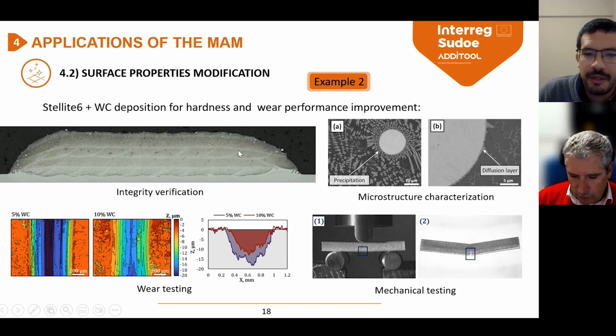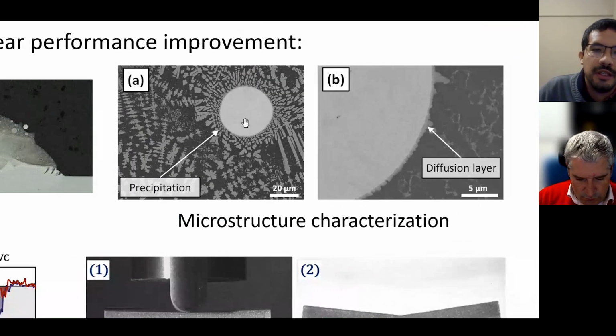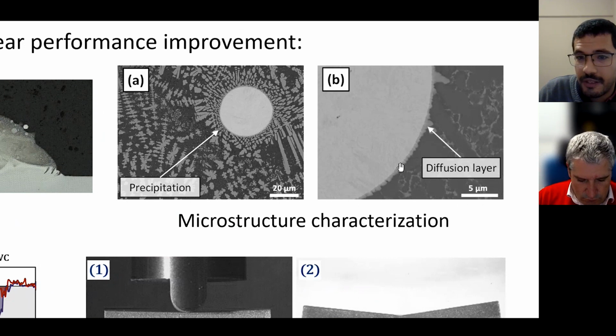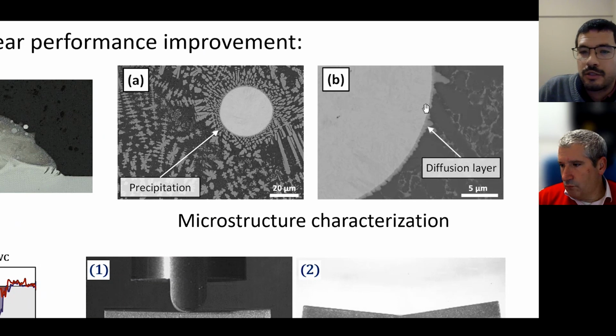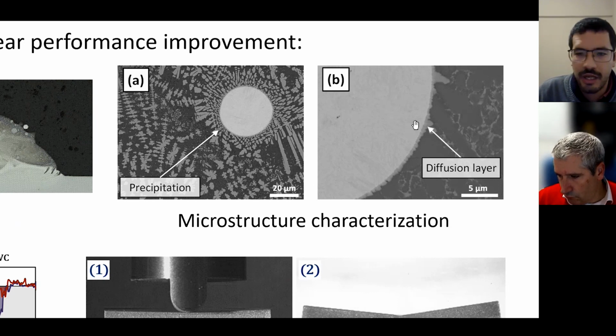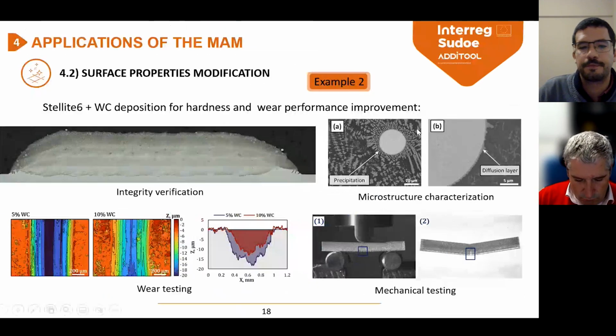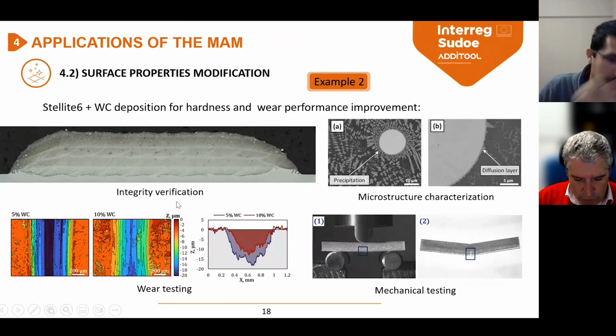Also, as we have a metal matrix composite, we perform an evaluation of the bonding between the tungsten carbide particles and the metal matrix. And as you can see in the right figure, there is a small diffusion layer, but it's so small that it doesn't affect the properties of the Stellite 6 matrix. And also this diffusion layer ensures the proper bonding between the tungsten carbide and the metal matrix.